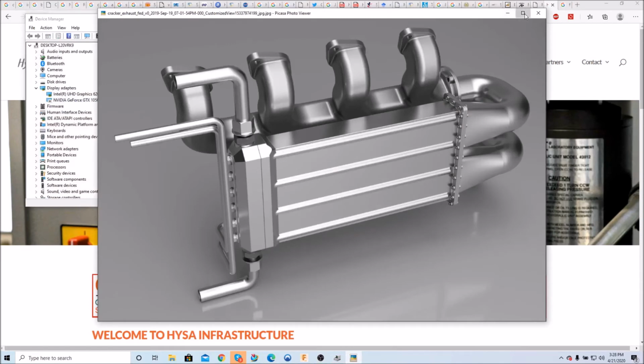the most important data is going to be the cost of manufacturing that reactor and its longevity. It was shown 1,000 hours is realistic, and they didn't push it any further than 1,000 hours. At least 1,000 hours. Minimal cost, $2,000 a kilogram capacity, and the potential to either harness exhaust energy or have a dedicated combustor module providing the heat for fuel cells. Because you don't have any heat from a PEM fuel cell, right? It's a low temperature fuel cell. And the rationale is because, well, it's low pressure, it's liquid, it's easier to handle, et cetera. Well, it's liquid under storage, but it's a gas under atmospheric conditions. But you pressurize it to 10 bar, whatever, it's a liquid.